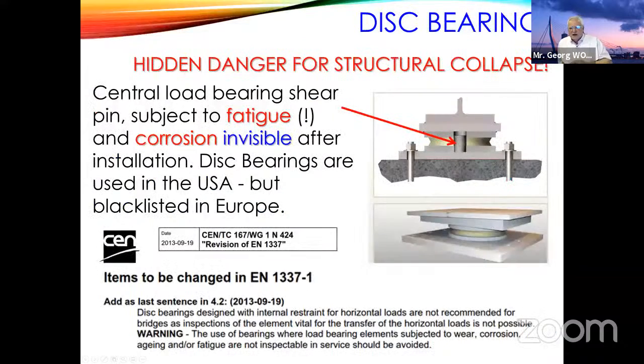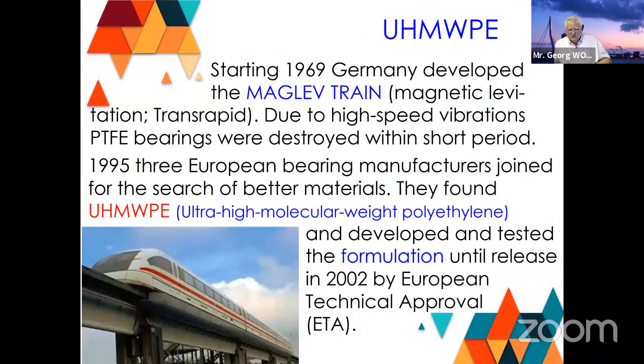So then in 1969, Germany developed the magnetic levitation train, Transrapid, which is today in service in Shanghai between the airport and the city. And there was a test track. And in this test track, there have been the PTFE bearings installed. And within a short period of some months, the bearings were destroyed because the train causes a very small movement with a very high frequency, like a sewing machine, and the PTFE couldn't cope with that. It has an incredible wear.